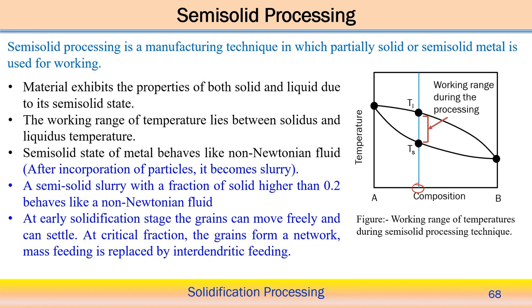So in that way we represent any kind of semi-solid component, particularly associated with the solidification of the metal. A semi-solid slurry with a solid fraction higher than 0.2 behaves like a non-Newtonian fluid. It means the semi-solid slurry has certain critical values of the solid component. And when you look at the complete solidification process at the very early stage, when there is growth of the grains, the grains can move freely because there are not so many obstacles from the presence of other grains. So in the very initial stage of solidification the grains can move freely and can settle down.